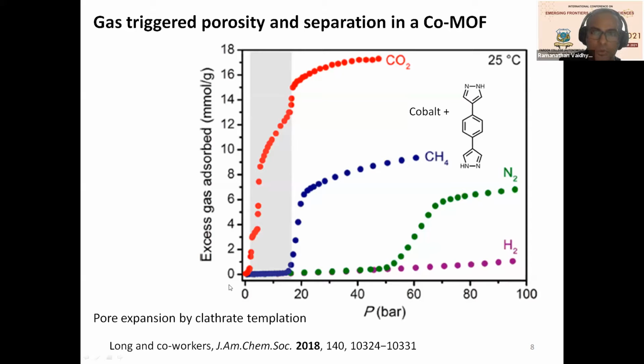Now, let us look at what CO2 does in the same MOF. You can see, unlike methane, CO2 starts to adsorb from a very low pressure, okay, almost like 0.1 bar or something. And then it immediately starts to fill up the MOF, and then it is taken up rapidly. But this also shows some mild structural changes. That is what these types of features represent. Okay. So now this gray area, can you see this gray highlighted area? This area represents where you can collect a large amount of CO2 selectively over methane if you have a mixture of CO2 and methane. Okay, that becomes very interesting.